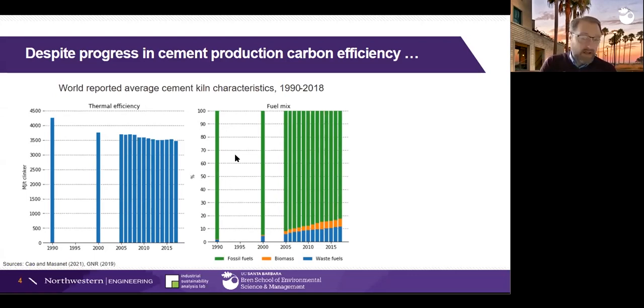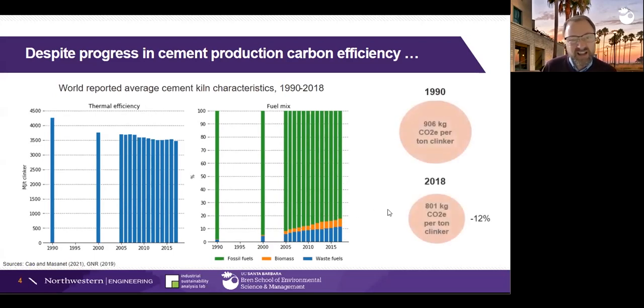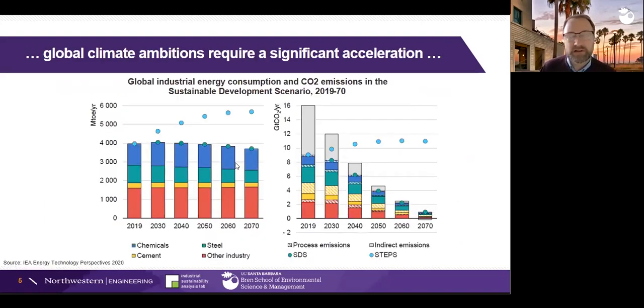And there also have been a lot of strides made in using lower carbon fuels within the kilns. What we see here is the mix of fuels, green being fossil fuels, blue being waste fuels, orange being biomass. We see a steady increase in the amount of low carbon fuels. Together, those thermal efficiency improvements and those low carbon fuel shifts over the last 30 years have significantly reduced the CO2 emissions per ton of clinker, going from around 900 kilograms per ton of clinker down to around 800 kilograms in the present day. So certainly some progress has been made.